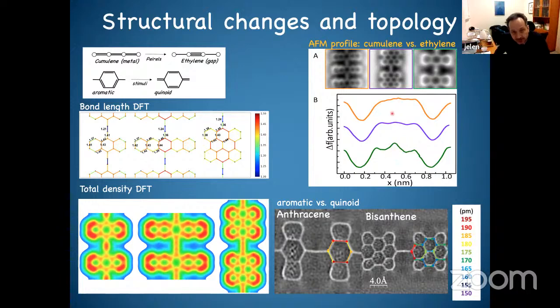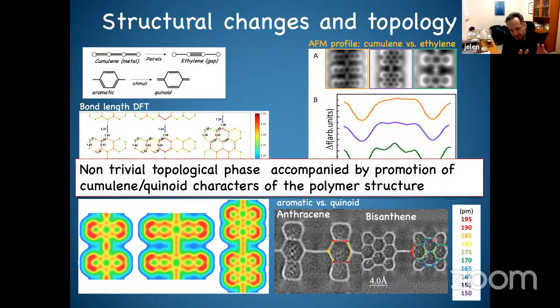So this triple bond has more repulsion than in this pentacene, and we also see this in this similar polymer, which has topologically non-trivial states. We can also have a look at the bond length, but this is more tricky, and we don't trust this too much because there are some distortions. But there is strong evidence basically here. What you see actually is this topological transition, which for condensed matter physicists is kind of evidence of edge states. In chemistry it means that I change the conjugation, okay? So it means that this topological concept, which is mainly adopted by physicists, could also be adopted by chemists. And I think it's a very interesting point of view because maybe people trying to understand this kind of pi-conjugation, what is the origin, what could be behind it, etc.